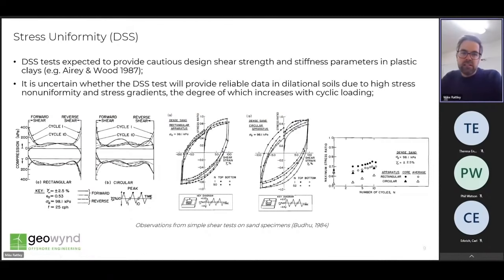Okay, the DSS test itself also suffers from some limitations in relation to stress uniformity, particularly for dilational soils. Although the test is expected to provide a cautious estimation of shear strength and stiffness parameters in most clays, this does mean that the test might not give representative measurements in dense sand, for example, where again some caution may be required. The impact of the non-uniformities is discussed in earlier research, as illustrated on this slide, so there are references out there to look at the potential impact.